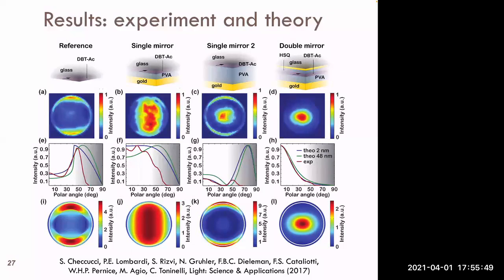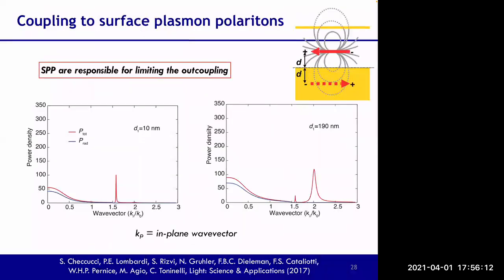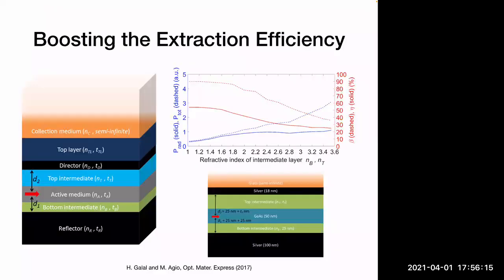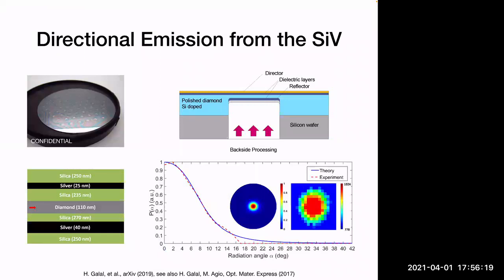And if you start to take these thin films, you see how strongly the radiation pattern changes. And if you go to the double mirror situation, that is what we proposed as a planar antenna, you see that the emission now is completely focused in the central direction with a very small angle. So this is very interesting, and maybe let me skip this because it's a bit technical. And we try to apply this to color centers in diamonds. So we created diamond membranes because the planar antenna unfortunately requires a very thin active layer. And so we went down to membranes of the order of 100 nanometer, and then we applied this thin film, in this case silver, spaced by a certain distance, which is required in order to tune the radiation pattern.